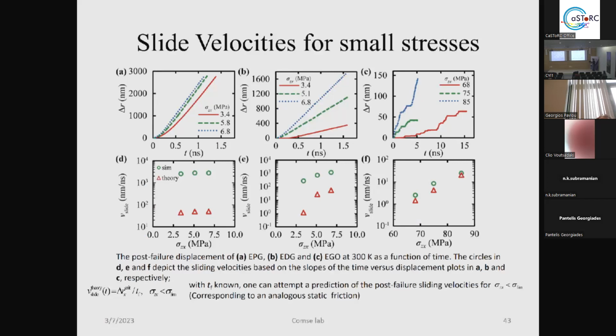In contrast, the defective graphene, due to the holes, has some better adhesiveness and has some better agreement between theoretical and simulation values. But of course, the best adhesiveness is the EGO system, where we can see a stick-slip phenomenon here. And of course, it has the best agreement between the theoretical and simulation.